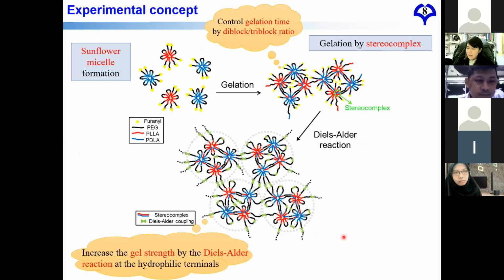So based on this idea, the corona micelle and the flower type of micelle will be very different. Actually, they have different sol-gel transitions and gel-sol transitions. I will mention that later. Using this kind of micelle, we can mix the corona type micelle and the flower type of micelle to make a new sunflower type micelle, and then have the gelation. And then we also introduce this Diels-Alder reaction to make more cross-linking between the micelles.